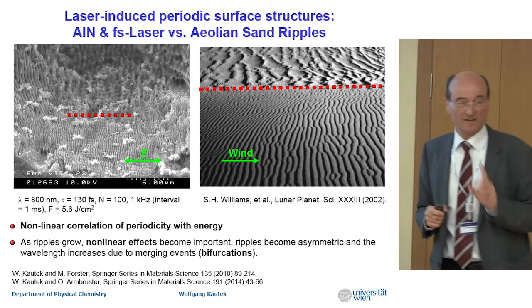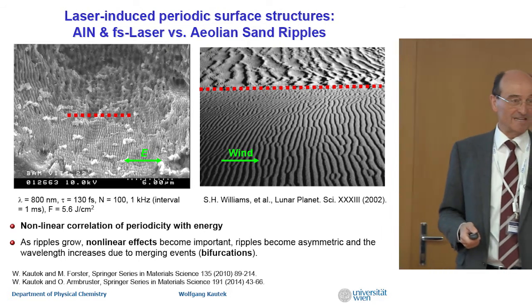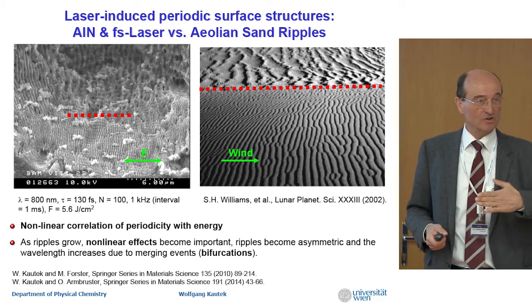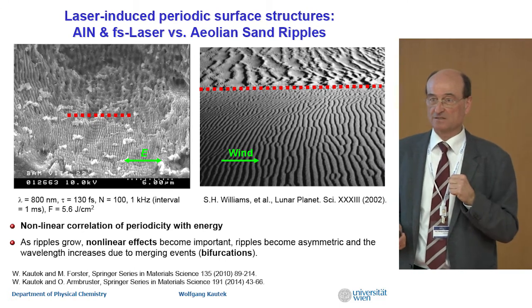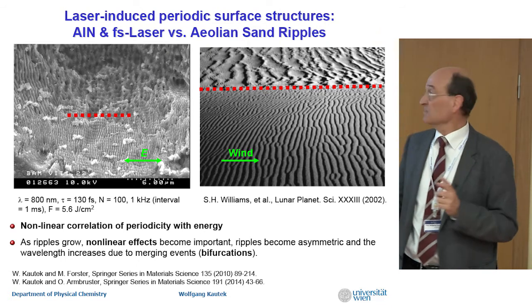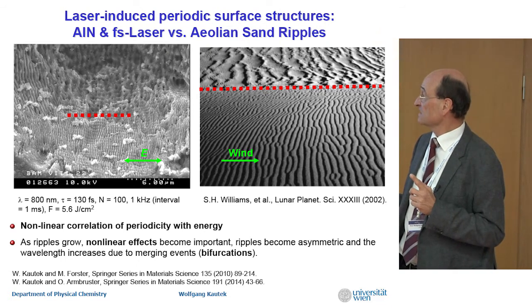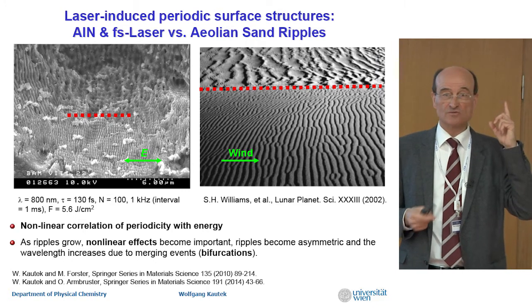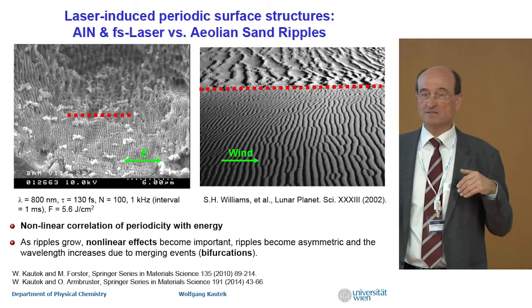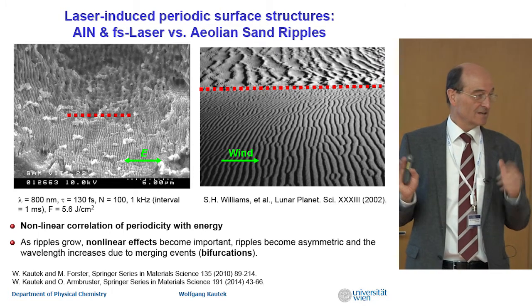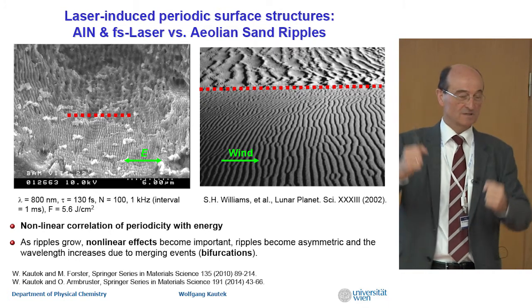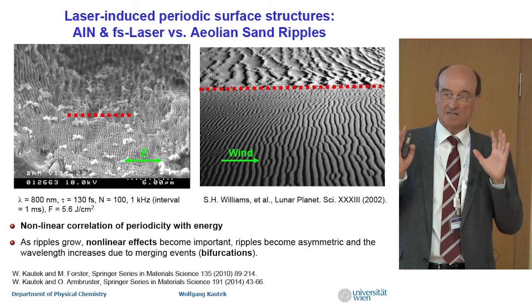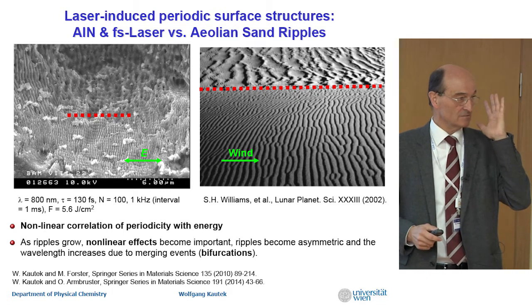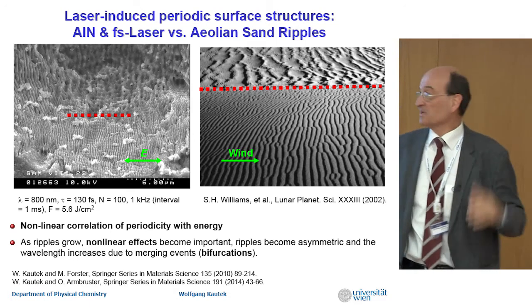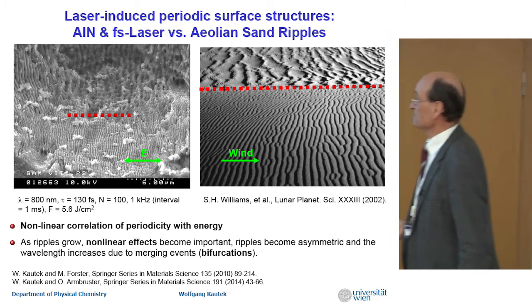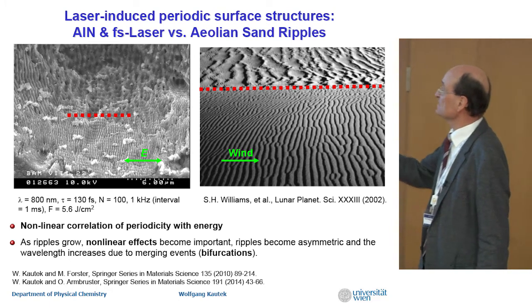Anyway, another feature which is very interesting is that the polarization of light is very important. You can turn the orientation by the polarization of light. Remember, we are exciting with femtosecond lasers, and the electrons are hot for a long time, then they dissipate, and the ripples are not there yet. And the ripple formation, the movement of atoms, takes much longer. So somehow the material has the memory of the polarization. It's dark. There is no light anymore, but the ripples are oriented. It's very interesting. So there's a nonlinear correlation of periodicity with energy, as you can see.